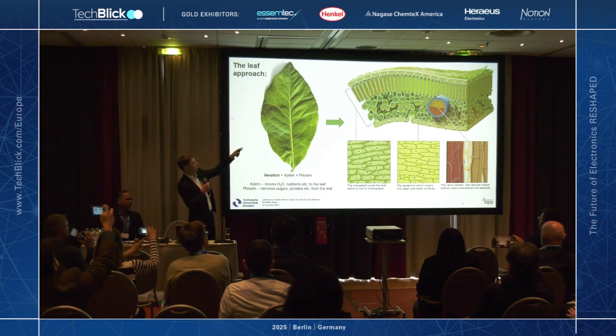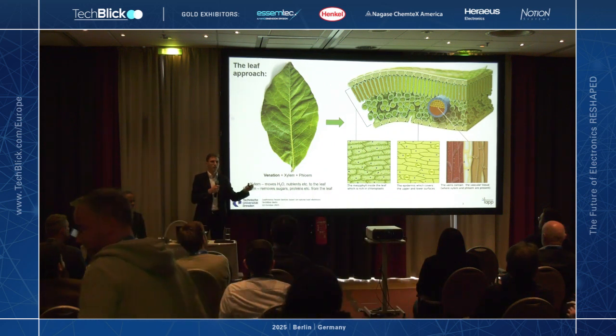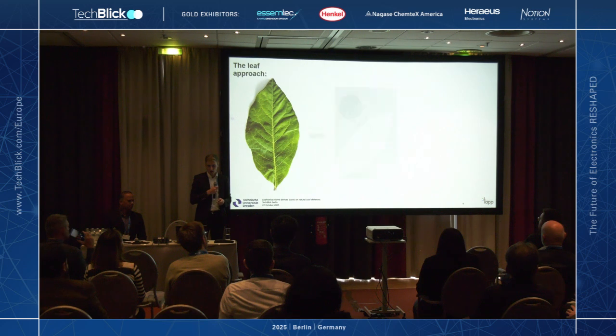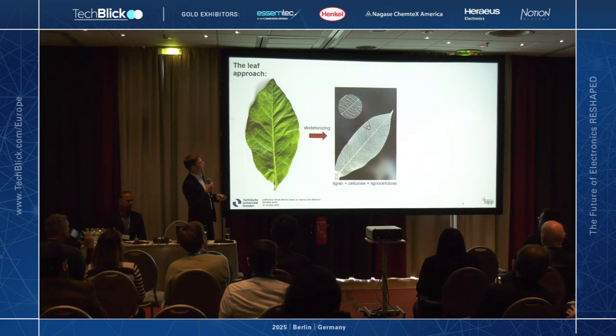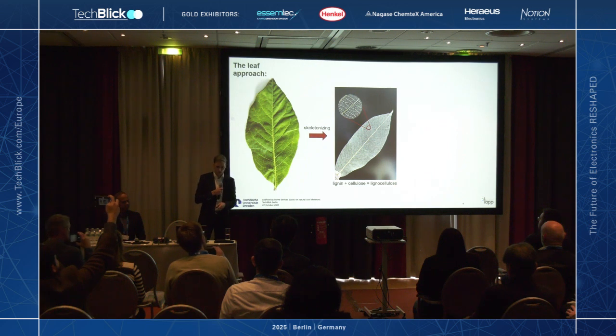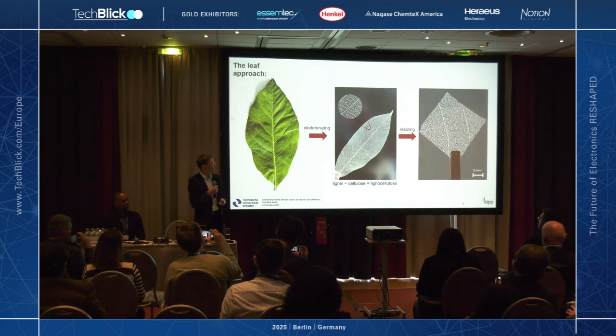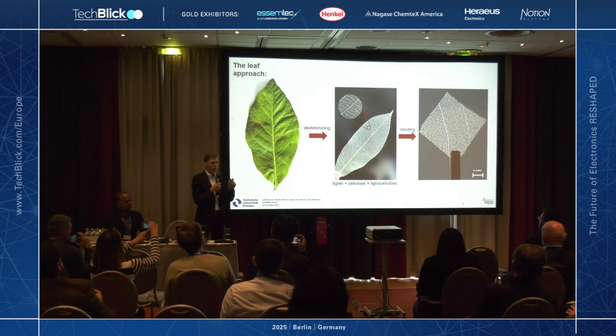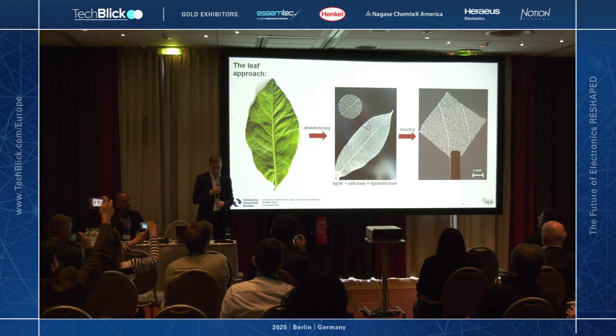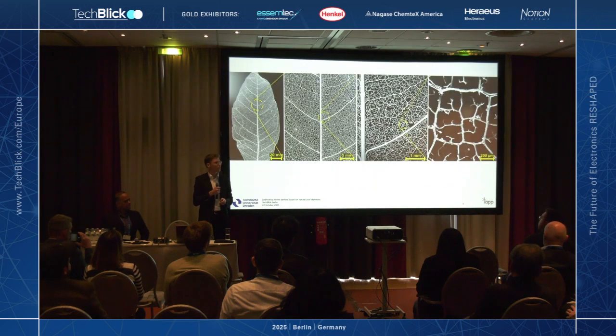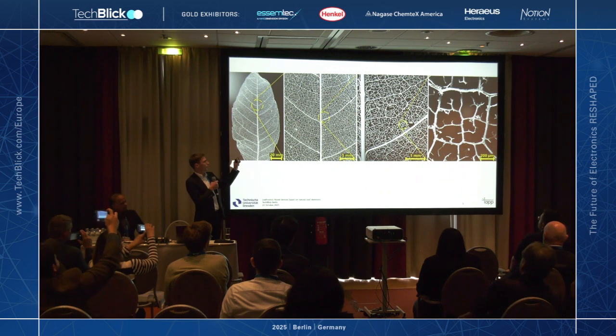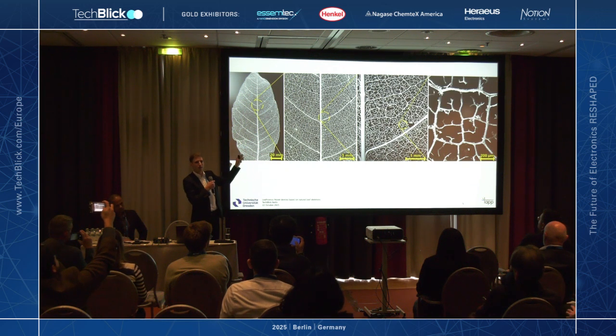And if you remove all the green stuff in this image, so the mesophyll, which can easily be etched out, you obtain a highly interesting structure which is made of lignin and cellulose. So this lignocellulose quasi-fractal structure, you can resize it to a smaller piece, and this can be used for substrate technology. The most interesting part here is that it is quasi-fractal, as I said, so it is fractal in multiple dimensions, so you go down into the micrometer range where it still can support the cells.